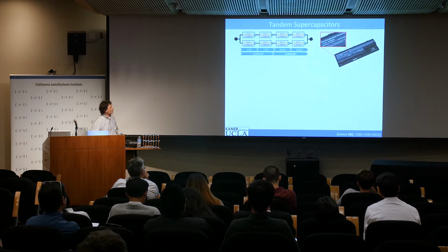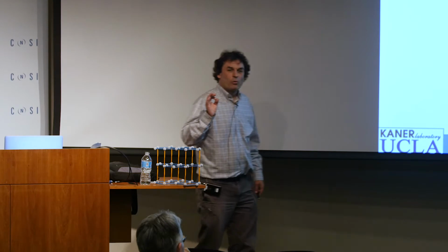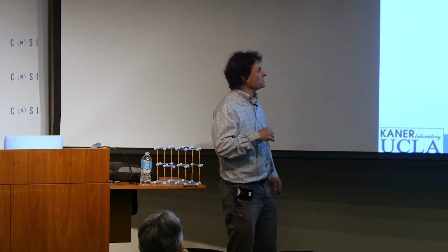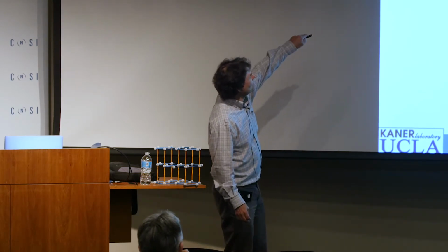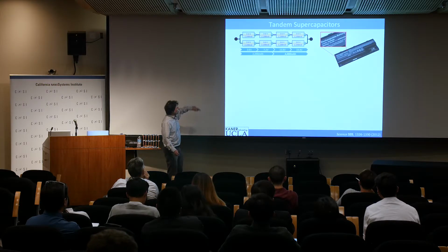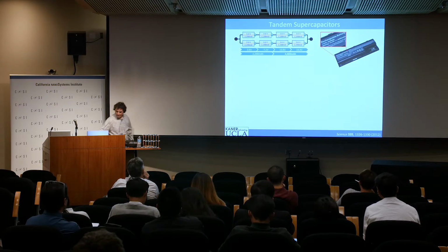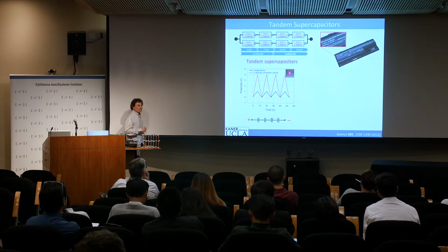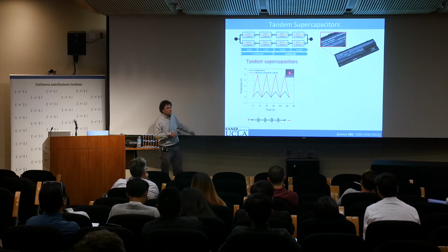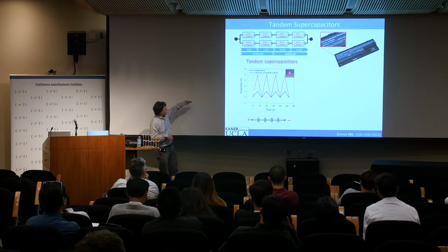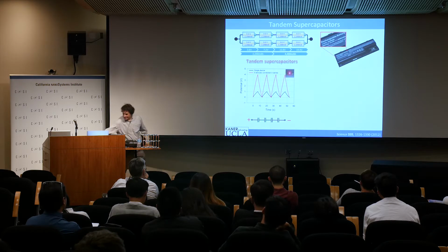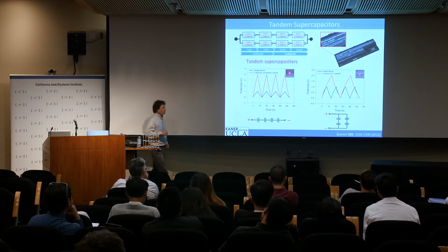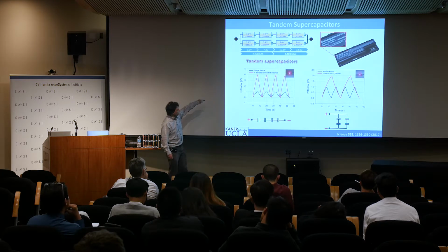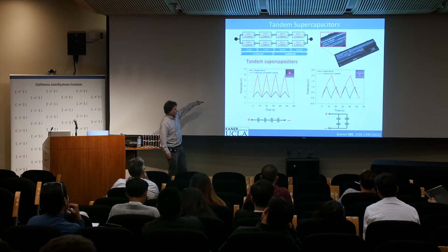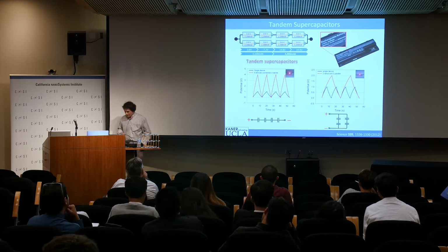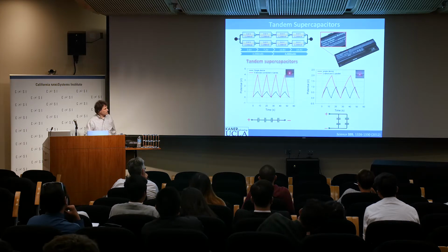Now, if you look at the back of your computer, it doesn't work on our 1-volt aqueous cell or even our 2.7-volt non-aqueous cell, but it works at 14.4 volts and 4,400 milliamp hours. But you can get that simply by putting things in series and parallel. So here's 4 1-volt cells put in series, and you'll see we get out 4 volts. Here's 2 put in series and 2 put in parallel, so we double the voltage from 1 to 2 volts, and we double the area under the curve. And these things are very low in internal resistance.